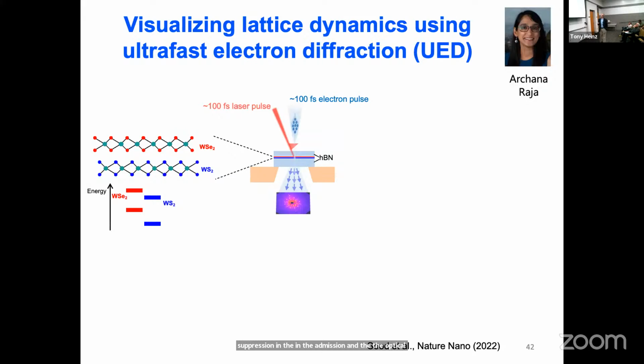And this is just a sort of highlights of some new experimental techniques. The other thing you'll notice is that if this interlayer exciton forms, then the energy of that state is lower than the energy you started. Where did the energy go? Conservation of energy, it should have gone into phonons. And that means in addition to the current flow, you should start the lattice vibrating.